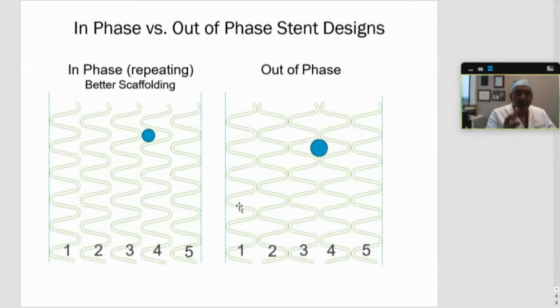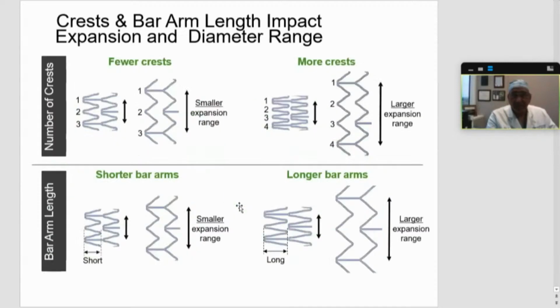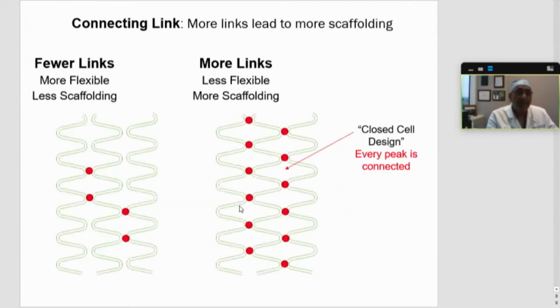As I described, the in phase and out of phase. So if something is in phase and it is very repetitive, it will give you better scaffolding. But if you're out of phase, it actually will give you more conformability so you can deliver the stent a bit better. So those are some of the trade-offs you have to decide when you're designing a stent. And as I described, if you have fewer crests versus more crests, you can expand it much larger if you have more crests. Also, if your bar arms are longer, again, you can clearly expand it much larger. Connecting link, as we discussed, the fewer the links, the more flexible the stents are with less scaffolding, the more the links, the less flexible.